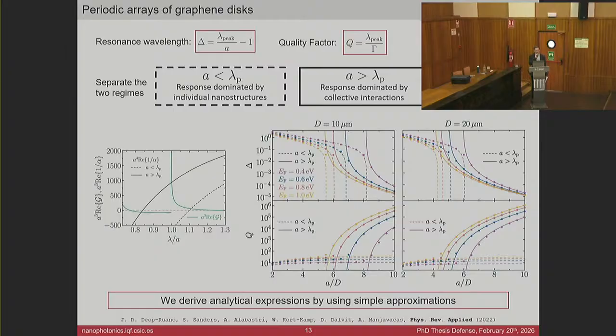There are other systems that are able to maintain a larger response. For example, when we use nanospheres, the extinction efficiency doesn't depend that much on the filling fraction, and somehow the decrease in the response of the nanostructure can be compensated by the fact that you have a higher interaction, and then the peak extinction efficiency is roughly constant, at least to some point. If your nanostructure disappears, everything disappears.